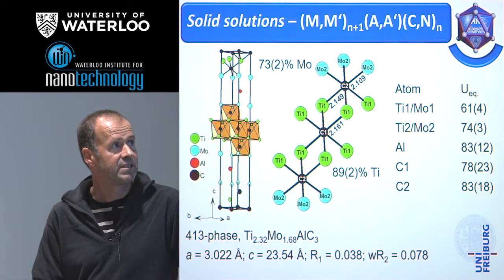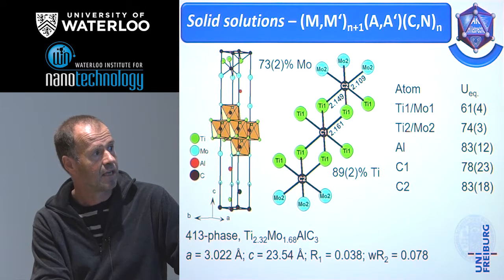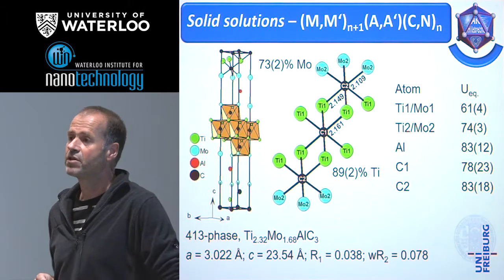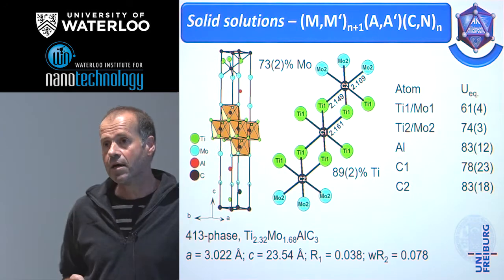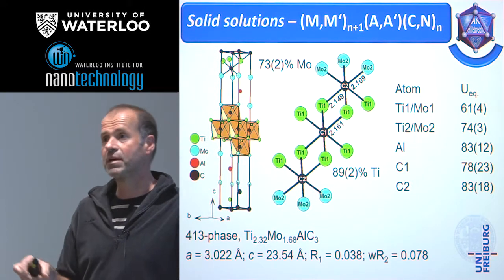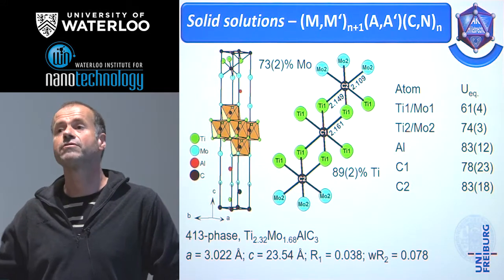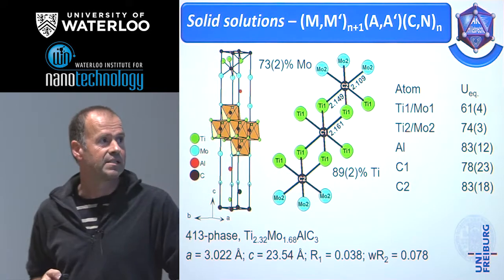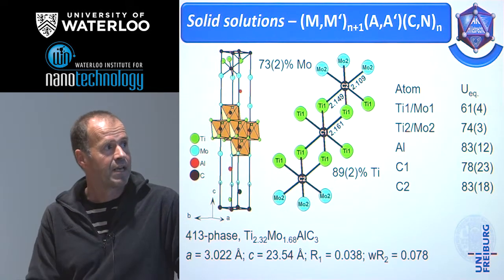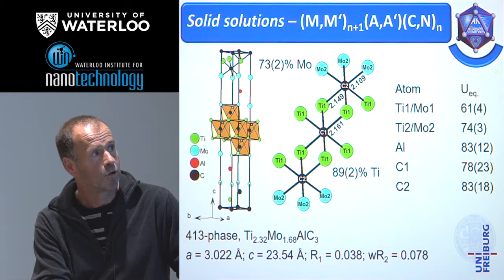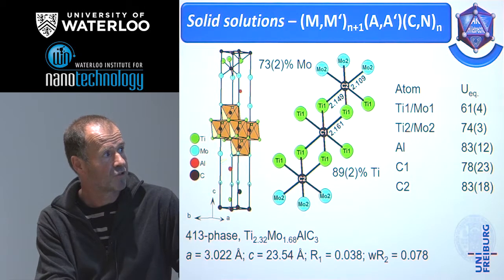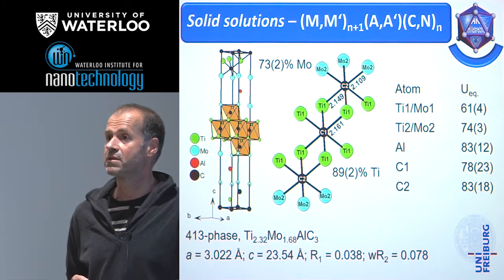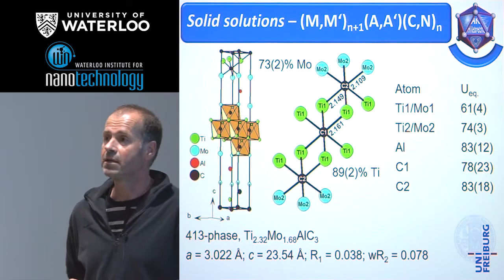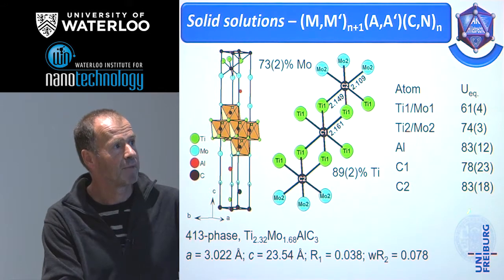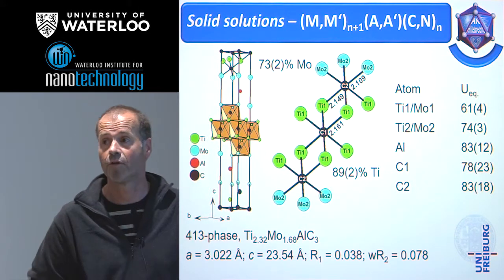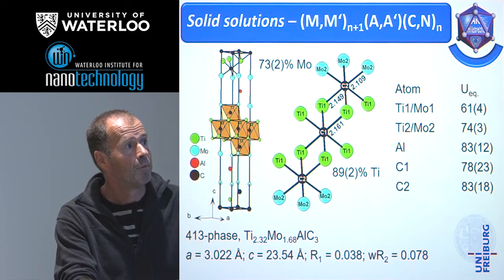So we could grow single crystals from this system containing titanium, molybdenum, aluminum, and carbon. And based on the single crystal data, we could show that the structure is disordered but with a strong preference of different sites for the single crystals. And some of the data show that the carbon positions are completely occupied. We can conclude from the displacement parameters, and the picture I've shown here represents a probability of 99%. That means the thermal displacement parameters are more or less isotropic, and the size of the displacement parameters shows that we have no deficit on the carbon side, and we also have no deficit on the main group metal side.